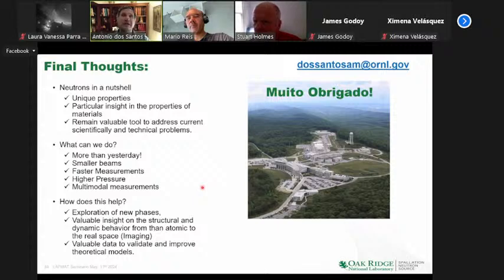So for the diamond anvil cell, we do have ruby measurements. The biggest challenge, I'm going to be very frank because we're among friends, is that when you go to a synchrotron, you have what they call a double membrane that monitors the load, because sometimes we have more than 1 ton of load on these presses, and as you cool, differential thermal expansion can vary the pressure by multiple GPa.